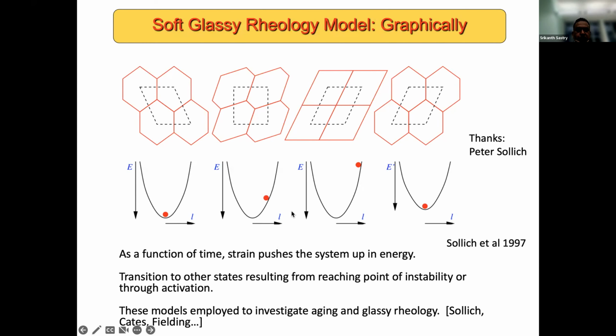Basically, when one reaches some kind of a threshold energy, the minimum in which the system is residing becomes unstable, and you make a transition to a new minimum. This new minimum has a minimum energy at the strain at which this transition took place, and therefore is a stress-free new state of the system. Okay, and this model has been studied extensively to understand complex glassy rheology by the original group of people, including Peter Sollich, Mike Cates, Suzanne Fielding, and so on.